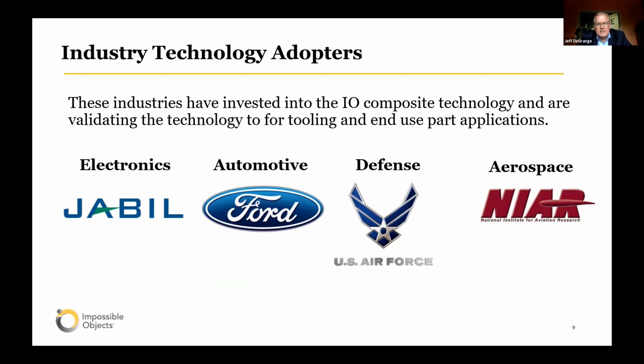Because of printed circuit boards, the product mix, the volume, and the constant change going on in the electronics industry, they have a lot of what they call surface mount tools. We found a number of different surface mount tools that can utilize the actual carbon fiber PEEK, which gives you the temperature resistance that's needed for a wave soldering operation. And then after so many duty cycles, it has to go through chemical washes. And the tools can be made faster at a lower cost than conventional techniques of making these surface mount tools